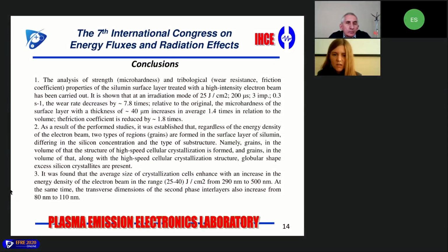So, some conclusions. The analysis of strength and tribological properties of the silumin surface layer treated with a high-intensity electron beam has been carried out, and it is shown that at an irradiation mode of 25 joule per square centimeter, the wear rate decreases by 8 times relative to the original. The microhardness of the surface layer with a thickness of 40 micrometers increases on average 1.4 times in relation to the volume, and the friction coefficient is reduced by nearly 2 times.